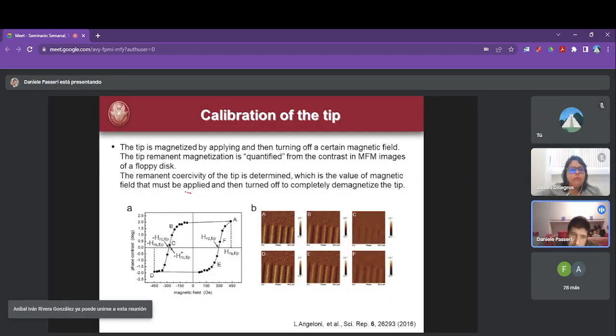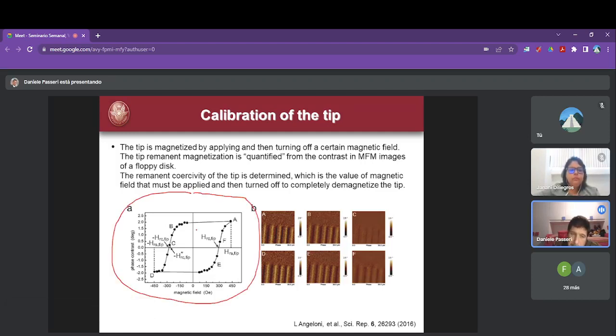Now, if we put again the floppy disk, what we did was to apply a certain magnetic field and then switch it off. In the end, you measure the contrast on the floppy. If you report here the contrast as a function of the applied magnetic field, which is applied and then removed, you have a curve which is the remanent magnetization curve of the tip. Remanent because it is what remains after the magnetic field is off. So you can measure these values, which is the remanent coercivity